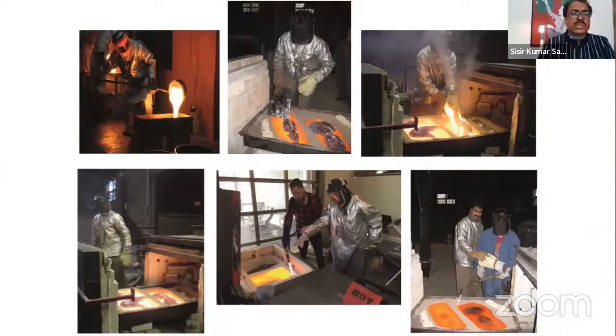Sometimes I pour outside the furnace kiln and sometimes inside the kiln. Here I am pouring outside the kiln. One can make a sand mold outside on the steel tray, SS tray, so that it doesn't get rusted. On the steel tray, one can have a plaster mold or sand mold and pour clear glass directly onto the mold.